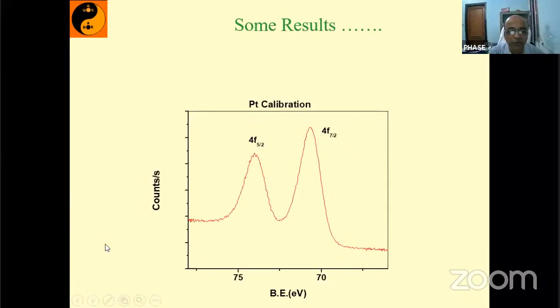Here you can see that as compared to the earlier spectrum, the noise is very less because of the complete alignment of the beamline, and you have a very intense source. That's why this spectrum is generated within 2 minutes, with a single scan only. In the laboratory, you will require multiple scans, 30 scans, 40 scans, 50 scans, depending upon your sample nature also.